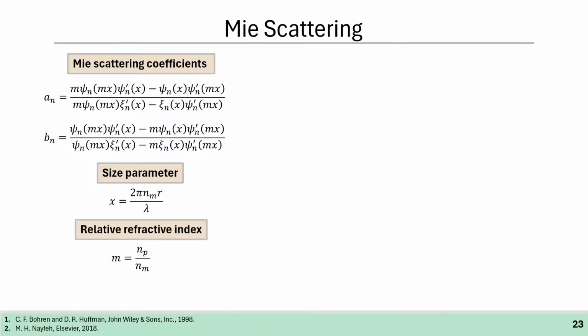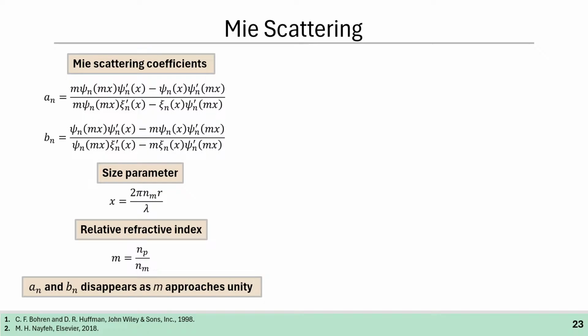Also, it depended on the relative refractive index, that is the ratio between the refractive index of the particles and of the medium. And if the refractive index of the particle and the medium are very similar, we basically won't be able to observe the phenomena, as the an and bn coefficients will disappear. So we need to work in conditions where our medium and our particles have refractive indices as distinct as possible.